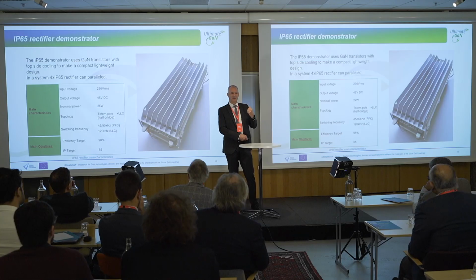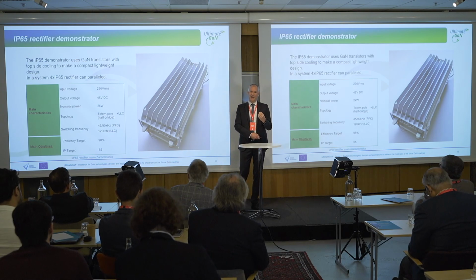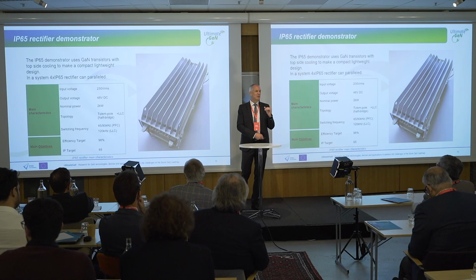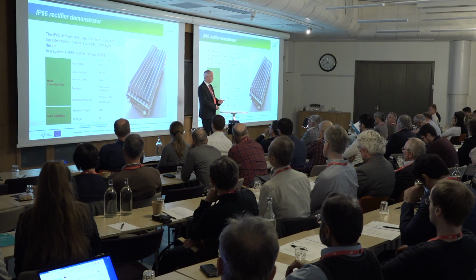And this is a signal, yes, gallium nitride, if you look at the yields and all the intrinsic reliability of gallium nitride is still on the learning curve, absolutely. But we managed it with really good stress testing, understanding the mechanisms to sort out the devices which could fail in the field. So there's a lot of know-how in how to test it, how to stress it, that you can manage it to have very good quality. And so I see a bright future for gallium nitride. Even though we still have to learn a lot in terms of defects, on reliability. But as a message to the audience, I believe we will manage this. And we did it also for silicon carbide. Also silicon carbide has a higher defect level than silicon, and we managed it to have good quality in the field.